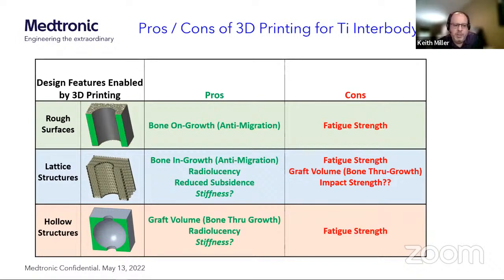So really, 3D printing gives us the opportunity to put three features in devices that you can't do with machining. One is a rough surface. I don't know if you can see at the top of that image, you see a rough surface there. We can actually engineer a rough surface that promotes bone on growth. So that's the pro of that rough surface. When you have bone on growth, you have less migration of the device. The con of that, though, is fatigue strength. I basically added more little notches on the surface of the device where fatigue fractures can start.